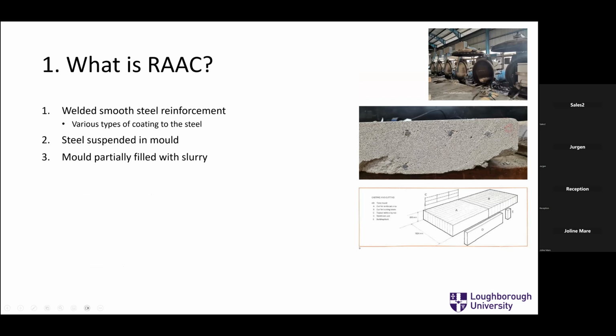So I think I'm saying I'm not here to bash RAAC. I've researched it and know it very well now. It's a different material and it's very clever, but it's also susceptible to abuse. Because it's lightweight, you can cut it with a handsaw. And certainly if you have a circular saw, you can cut through the rebar because the rebar is typically 6 millimeters, 8 millimeters, maybe 12 millimeters at most. But circular saws, which you get on every building site, will cut through it really quick. So it does get abused a bit on site, which I'll come back to, and has been one of the problems.